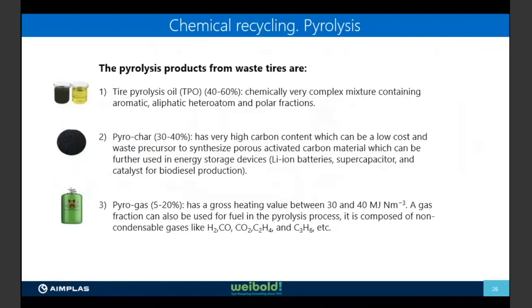The second one is the pyrochar. You achieve between 30 and 40%, and it has a very high carbon content, which can be a low cost waste precursor to synthesize porous activated carbon material, or, as Luis has said before, carbon black. And the third one is pyrogas, which you achieve between 5 and 20%. This gas fraction has non-condensable gases, mainly hydrogen.